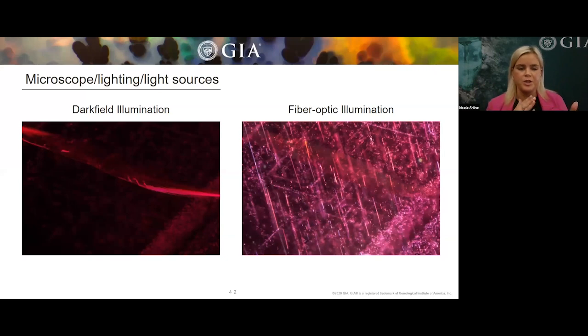So the image on your left is a Mozambique ruby just being shown with dark field illumination. So you can see that there's a feature breaking the surface. You got some particles behind it. But when you don't turn off that dark field and you just use that fiber optic light, the silk that is just commonly found within Mozambique just lights right up. So dark field versus fiber optic, you're just seeing two very different features from these rubies.